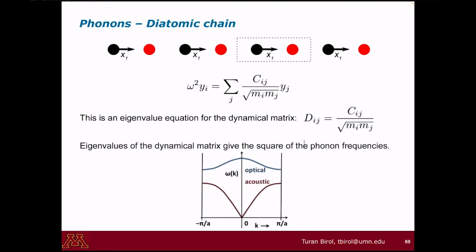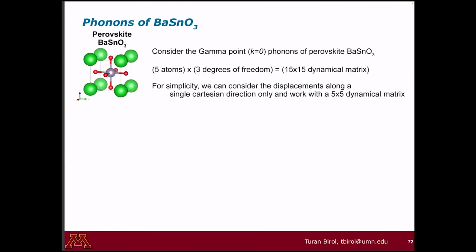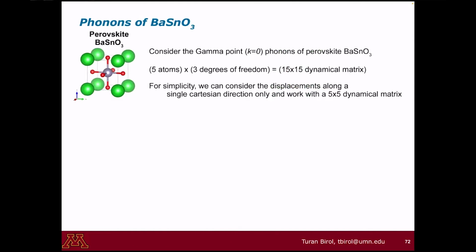But anyway, in the end, you obtain some dispersion like this in 3 dimensions with a big unit cell. You end up with something like a spaghetti plot where you would have tens of lines in the phonon dispersion plot. Even though many codes do this automatically, also there are some post-processing and pre-processing tools like Phonopy, which does this automatically with varying degrees of accuracy. It is good to actually know what the phonons look like, what their form imposed by symmetry is.